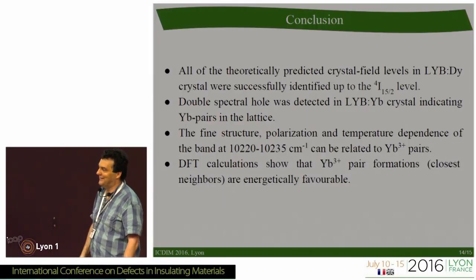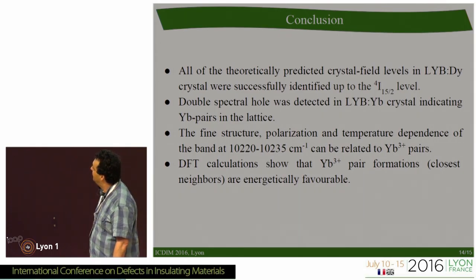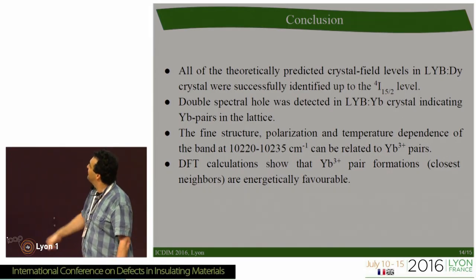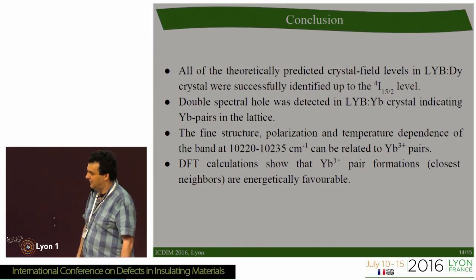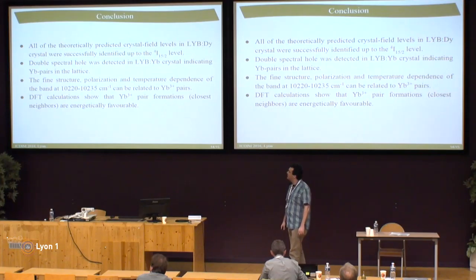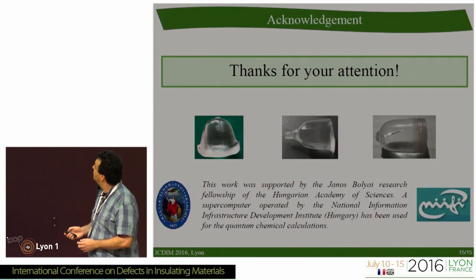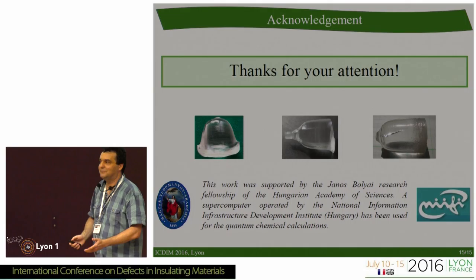In conclusion: for dysprosium-doped lithium yttrium borate crystals we successfully identified all crystal field levels up to that manifold. We showed a double spectral hole in ytterbium-doped lithium yttrium borate, and showed that the ytterbium pair absorption band has a fine structure. Calculations showed that ytterbium pair formation is energetically favorable in this crystal. Thank you for your attention.